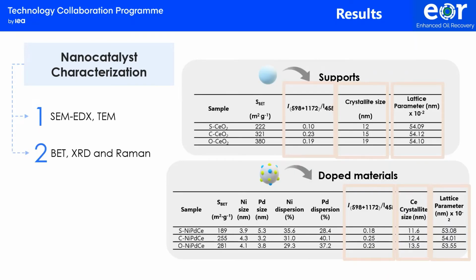For the X-ray diffraction results, it is observed that with the change in ceria shape, the lattice parameter is slightly affected, being higher for the cubic nanoparticles. Also, the crystallite size through the 111 orientation increases in the order spherical, cubic, and orthorhombic ceria nanoparticles. Therefore, crystallinity follows the opposite trend.